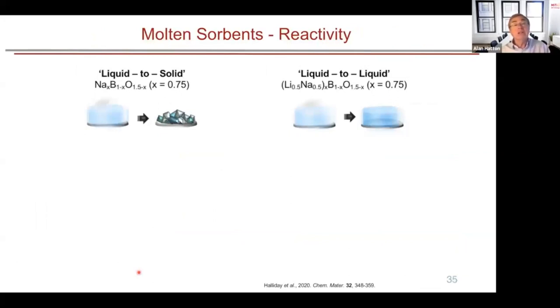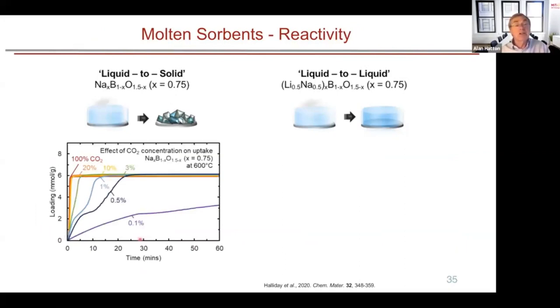Just to show you quickly some results of these, this is a liquid to solid type system. This is the loading as a function of time when we challenge these sorbents with CO2, and you'll see that depending on the concentration, there's always this little knee that comes in here. We get a fairly quick absorption rate and then a bit of a knee. At this particular point, the sorbent is becoming saturated with the CO2, but you're also getting nucleation and formation of particles as shown here. Once that occurs, that keeps on driving up the CO2 loading to a full loading on the order of 6 millimoles per gram, which is pretty respectable.